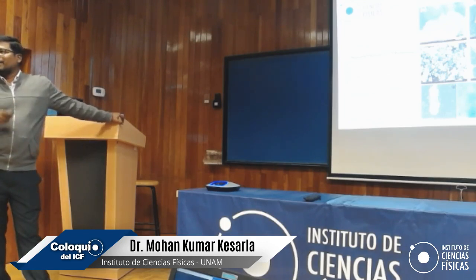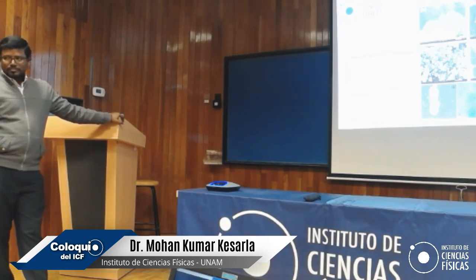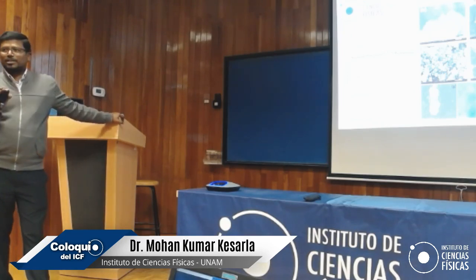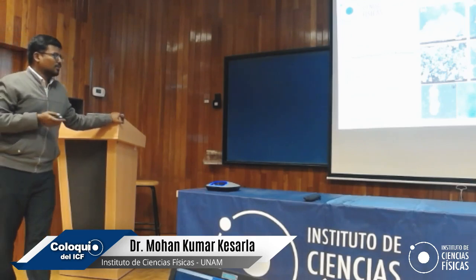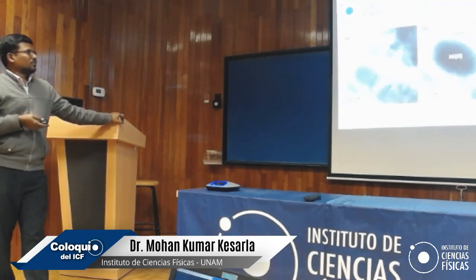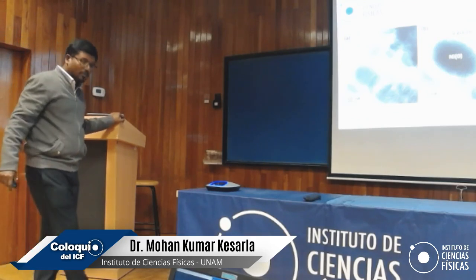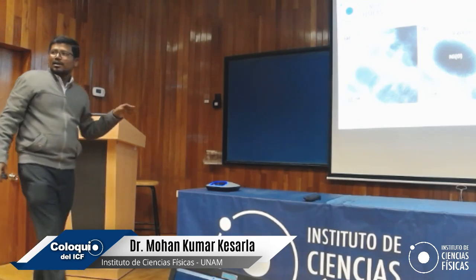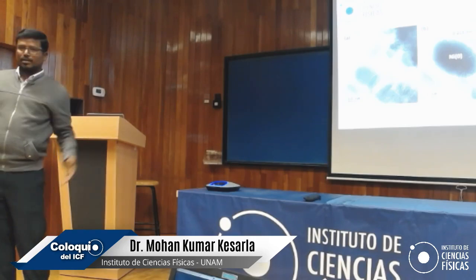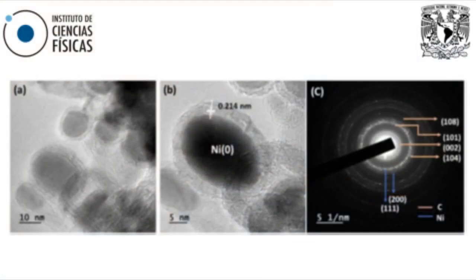What happens? It is fine up to the immobilization of nickel onto the g-C3N4, but after the heat treatment, the phase of g-C3N4 is entirely gone, and there is a new phase of carbon, and we don't know what is happening. So we tried to analyze, and once again thanks to our technician Joseva, he told us there are some coaxial kinds of structures in the material. So we went through high resolution transmission electron microscopy.